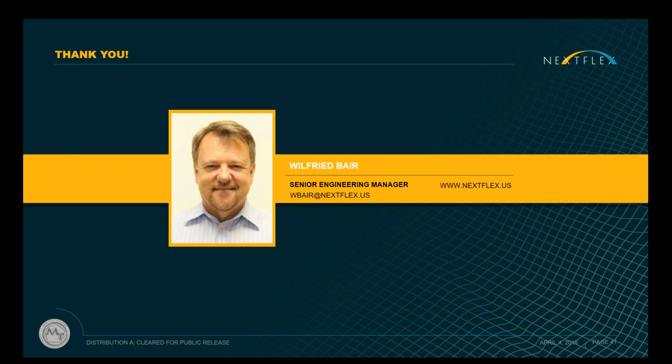Okay. Back to die attach. Does the die attach limit the speed of the SoC? If the die attach is done properly with the right ACP combination that's suited for the conductors, we did not see any difference. We did evaluate, just on that note, about 5 different ACPs to see which one works, varying by particle size and chemistry.